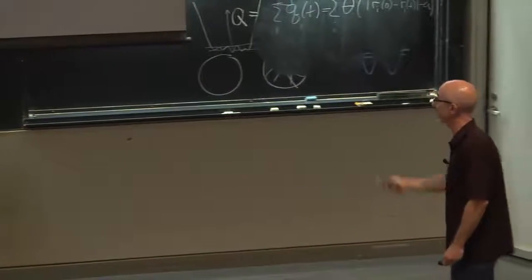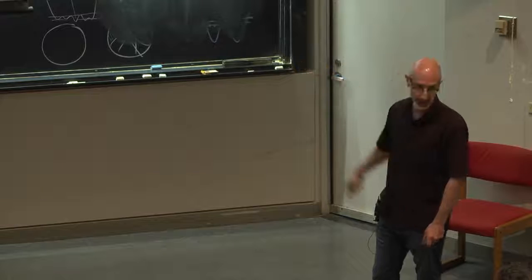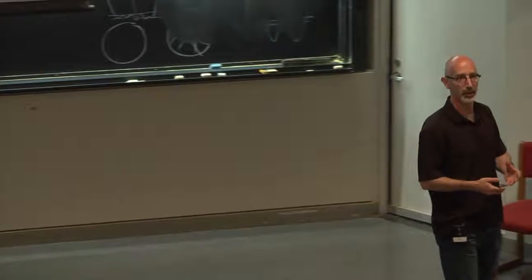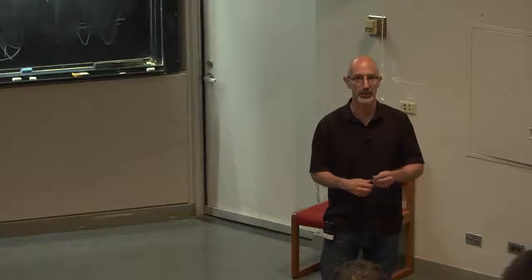If you then try to extract that length scale by generalizing to the structure factor of the overlap, you can do your best to try to fit this to something like an Ornstein-Zernike behavior. And what you generally find is that there is a length scale that's growing. And depending on what system you want to simulate or what system you're looking at, the length scale grows, let's say, from 1 particle diameter to something like 4 or 5 particle diameters as you get to the temperatures where simulations become hard to do.